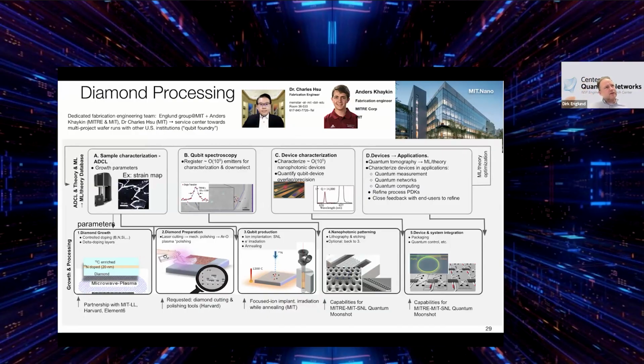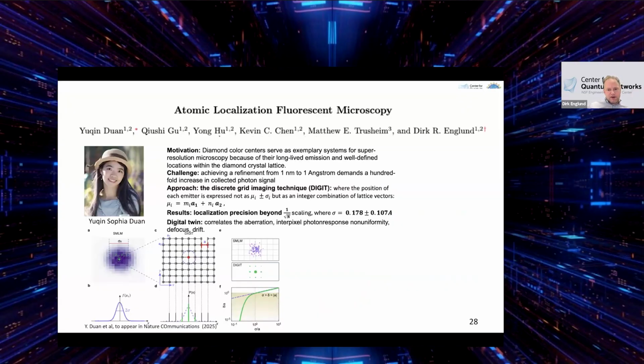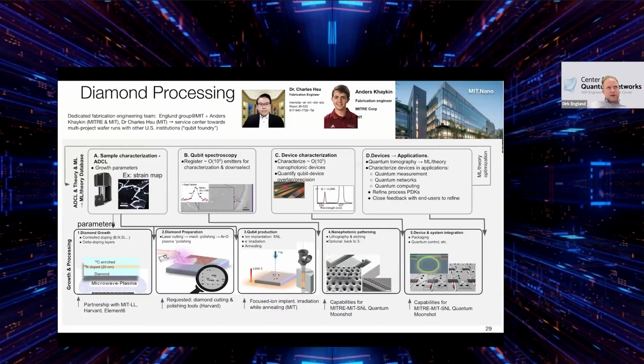And when you decay faster, that means your radiative quantum limited line width becomes broader, and you can shift what are naturally not so good emitters into a regime where they are good. In particular, what this would mean is that the line width of emitters radiatively limited, quantum mechanically, would be more here, like 400 megahertz or so. Now, if you have this additional broadening, whatever gave rise to this spread here, eventually that becomes negligible if you have sufficiently high Purcell factor. And that's probably the chief way to deal with this problem at the moment.